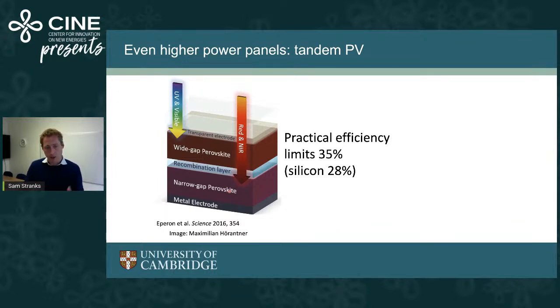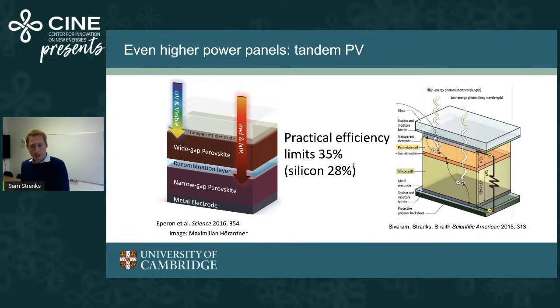But on a practical level, when we think about practical materials, it will push it up to about 35% efficiency. And so that doesn't seem like much, but when we compare it to silicon's limit of around 28%, it's really very big. And this is silicon as a single junction, a very big jump in terms of power output. When we think about these materials and these cells generating power for many decades, and also given the knife edge economics of solar or PV, this would be a game changing efficiency breakthrough at a cell level. And so that's an example of a perovskite tandem.